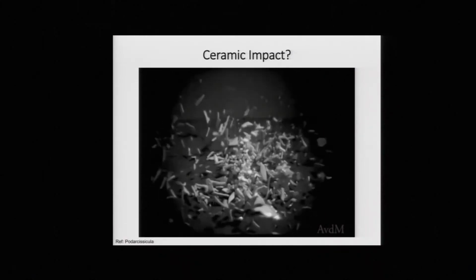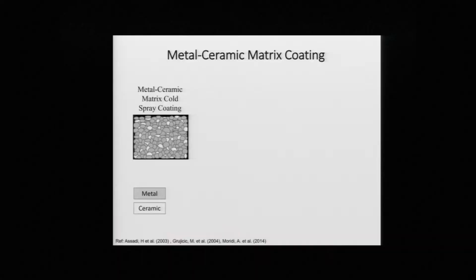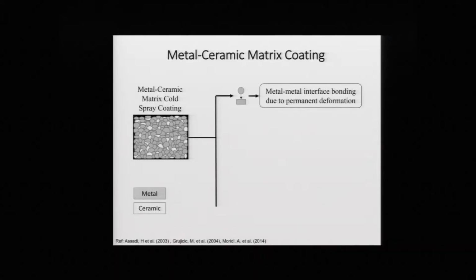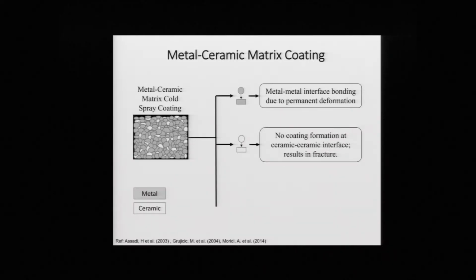But luckily, we can create metal matrix composites by cold spray. So let's see what's happening there. When we spray these coatings, we have both metal and ceramic powder being sprayed simultaneously. And when we spray these, we have 4 different types of interfaces. A metal impacting a metal, which bonds, as we explained, through that plastic deformation. A ceramic impacting a ceramic, which unfortunately does lead to fracture.